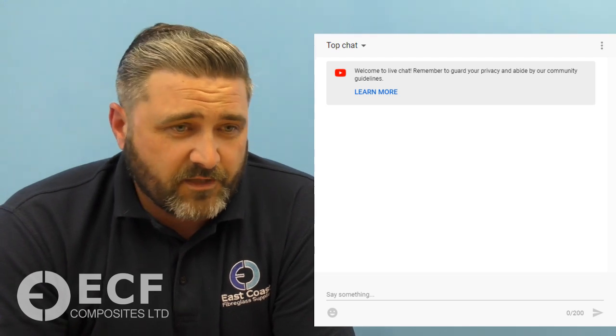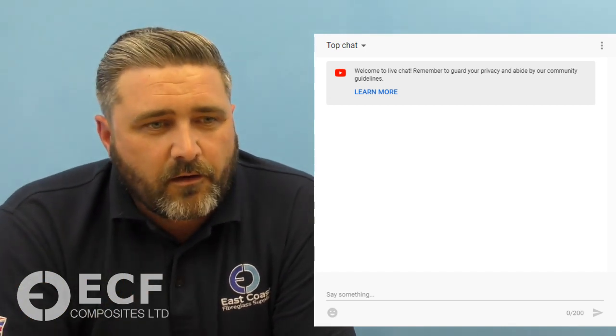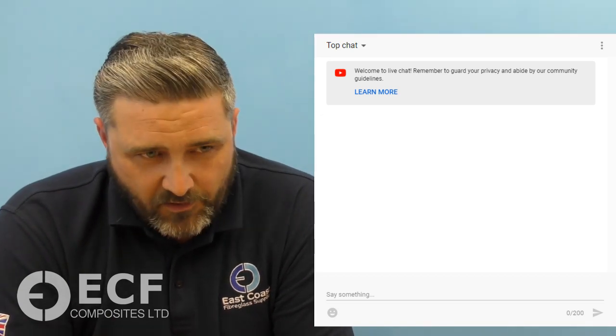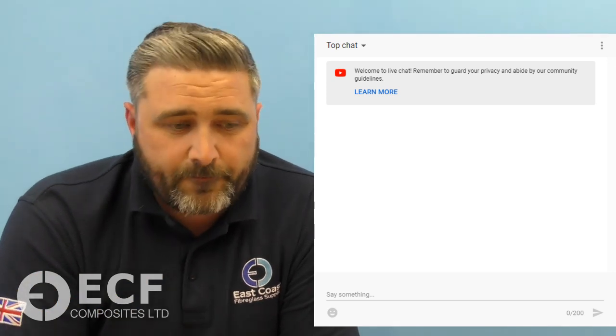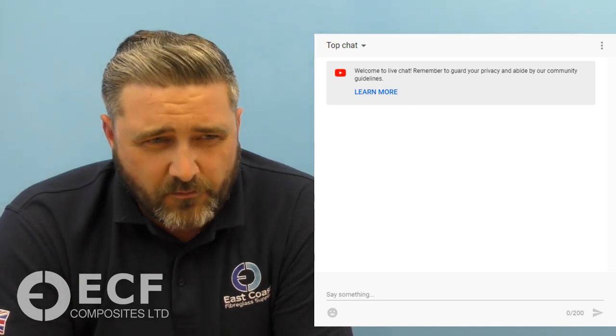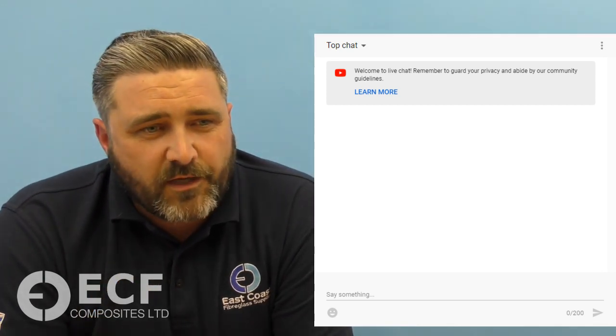A lot of it's down to either poor preparation or they're just not getting 100% chemical bond to an old laminate, or they're going on top of old paint or epoxy that gel coats don't bond to, because gel coat and flow coat is a polyester material. It relies on a chemical bond, so it has to go on top of another polyester. You can thoroughly sand epoxy and get somewhat of a mechanical adhesion, but it's not that great. As soon as there's a knock or a bash in that area, usually it will pick away from epoxy. So it's quite a long-winded answer to that question. It gets quite complicated when you start flow coating and gel coating, but I hope that clears that one up.